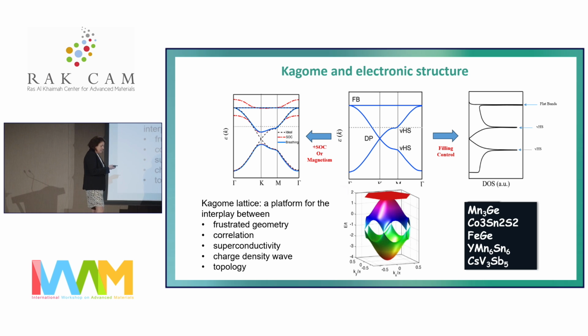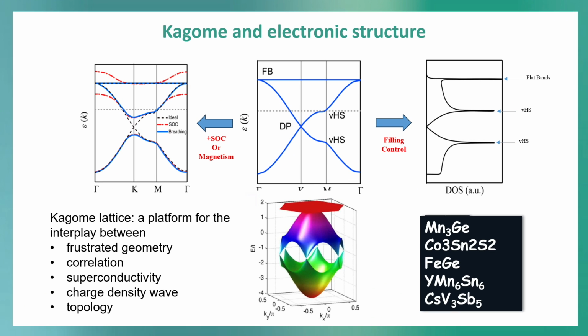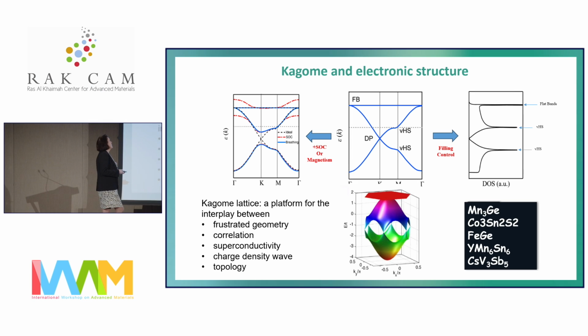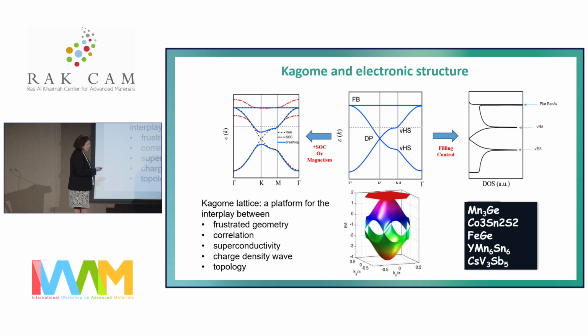So this leads to features in the density of states, which are these very high peaks in the electronic structure for the Van Hove singularity, and for sure a very big peak for the flat band. And some people also think flat bands lead also to superconductivity. So this is a three-dimensional sketch. You see here the flat band, and you see here the Van Hove singularity. One part of the band goes up and one part of the band goes down, and you see here the Dirac cone, similar to what we know for graphene. And if we apply spin-orbit coupling or magnetism, at this crossing point we can open a gap here, which leads then to very interesting surface states, as we already know, and non-trivial topology in this material.